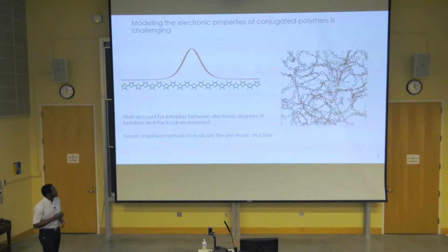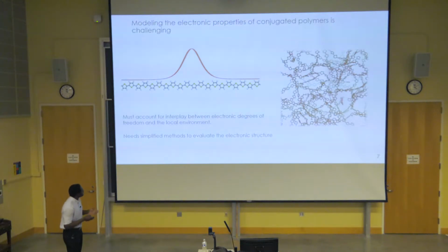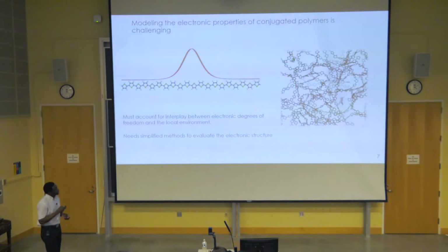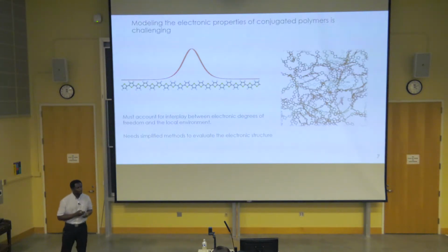It turns out that studying the electronic properties of polymer materials, and particularly accounting for structural changes, one has to take into account the complex interplay between the electronic degrees of freedom and the nuclei degrees of freedom or the local environment within the material. And also, in order to study phenomena such as charge localization, one has to look at large system sizes, and if one has to take into account disorder, one has to average over many configurations of the system in order to obtain a representative quantity. And these are prohibitive for first principles methods such as density functional theory or higher level quantum theories.